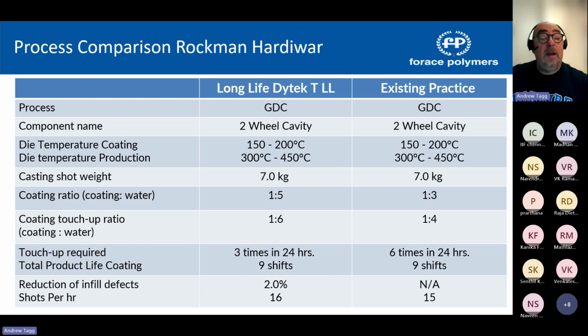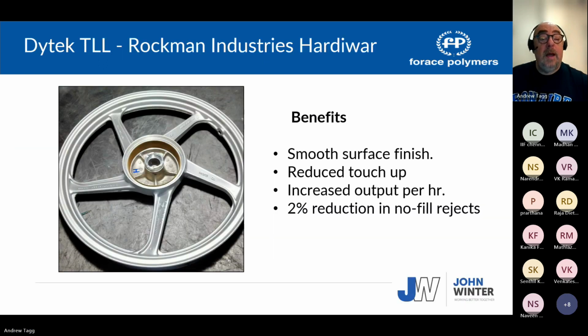This is a Rockman Haridwar. Again, shots per hour increased, and the number of times the touch-up was only 3 times in 24 hours compared to 6. Again, this was prone to no-run defects on here, and again, we reduced those defects.